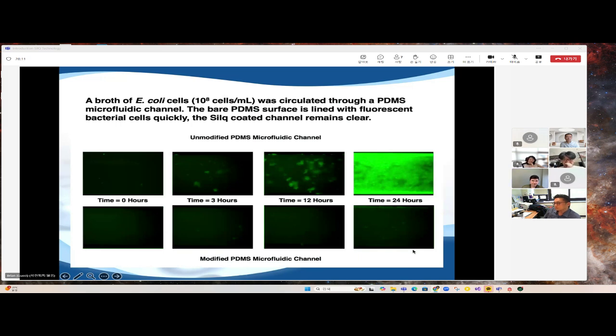We did that with bacteria that fluoresces, so we can see it under a microscope, just like we did previously on the discs. And we took E. coli bacteria, we pushed them through the channel under flow conditions, and after 24 hours, you can see that the entire channel made out of silicone is covered in biofilm. So tons and tons of bacteria lining the walls of the channel. We did the same experiment with the zwitterionic surface treatment, the SiLQ surface treatment, and you can observe again the effect on the bottom panels under the same conditions.